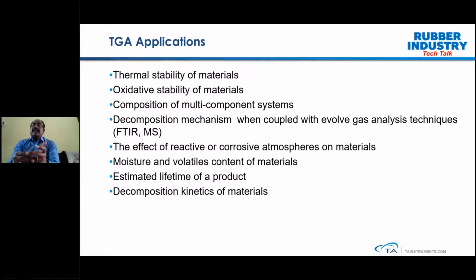Another aspect is the oxidative stability of the material. The polymer can be exposed to elevated temperature conditions where there is a higher chance that oxygen can attack the polymeric material, and there could be degradation. So TGA can help you evaluate that aspect also. The third is the composition of multi-component systems. Rubber polymers consist of many components: highly volatile components, plasticizers, the polymeric component, fillers, and oils, all mixed together.